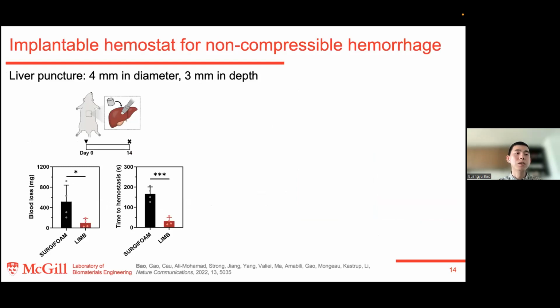So by leveraging the adhesion and also blood coagulation, we have used our bioadhesive as a non-compressible hemostat to treat non-compressible hemorrhage. In a rat model, we created a volumetric loss on the liver and applied the hemostats. Compared to the commercial product, Surgifoam, which is a hemostatic gelatin sponge, our adhesive reduced the blood loss and stopped the bleeding much faster.